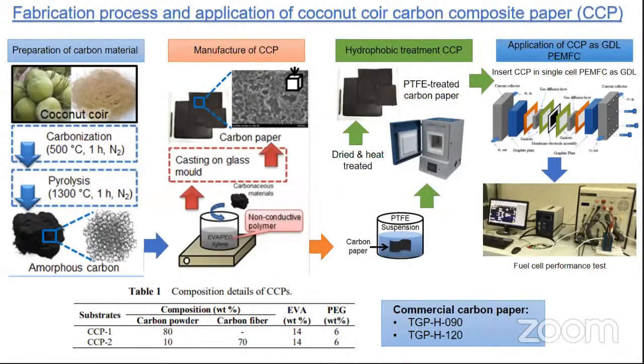Okay, for the details of the experimental method, we start by preparing the carbon material from coconut coir. Carbon material was produced in two different forms, carbon fiber and carbon powder. Both carbons were obtained from coconut coir by carbonization and pyrolysis. For the carbonization process, the coconut coir was heated at around 500 degrees Celsius under a nitrogen atmosphere, followed by pyrolysis at higher temperature, up to 1,300 degrees Celsius under nitrogen, to obtain conductive carbon material with high carbon content.